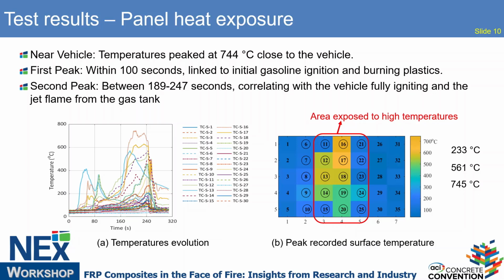The first peak temperature is within the first 100 seconds. It's because of the initial gasoline ignition and also the burning plastics. And the second peak, which is around 189 seconds to 247 seconds, is due to the vehicle fully igniting and also the jet flame from the gasoline tank.